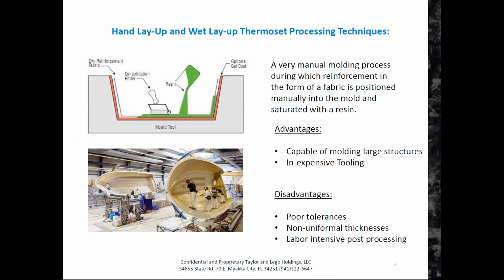So basically, this approach is just you apply fiber, resin, until you build up your desired thickness. In most instances, they'll vacuum bag it. There are people that still do not do that, and those people will have even worse variation in thickness. If you did a boat hull like the one these people are standing in, they probably have a variation in thickness of 1 inch from one end to the other, to give you an idea. At least 1 inch, possibly even 2 inches. So imagine you end up with a lot of resin richness or resin deficiency, and neither of which is good.